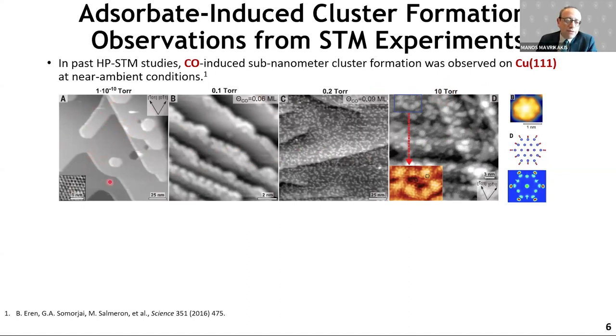So what is shown here on the left-hand side is a copper single crystal, copper 111, the hexagonally packed surface, the most stable facet. This is a terrace of this hexagonally packed set of atoms. This is another terrace here, another terrace. Notice the yardstick here is 25 nanometers under vacuum, okay?